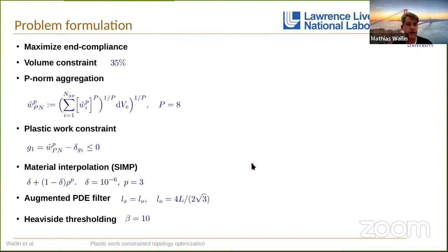Okay, so now to the elastoplastic problem. We do minimization of end compliance, and it's vaguely motivated by low cycle fatigue, since you do allow a certain amount of plasticity for low cycle fatigue. We have in all examples a volume constraint of 35%, and then we take the P norm in order to pick the maximum plastic work, and P is equal to 8 in this case. So we look at each Gauss point throughout the structure, raise that to the power P, and then we have a constraint on this. We allow a certain amount of plasticity, the maximum peak plasticity in the structure.